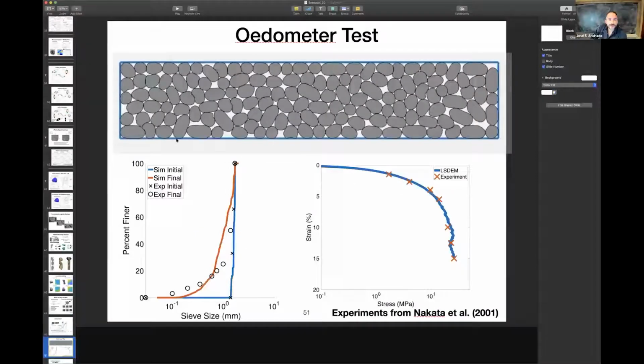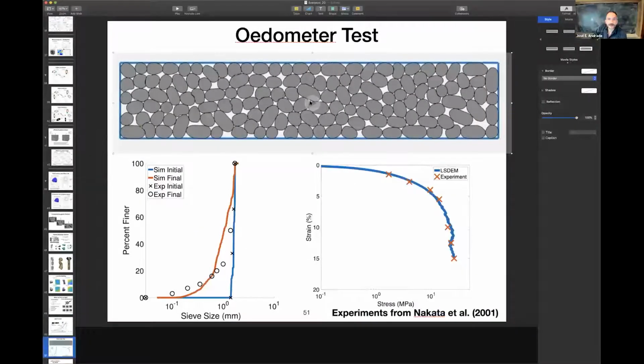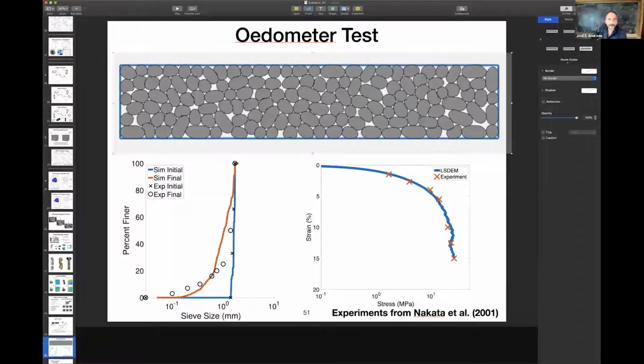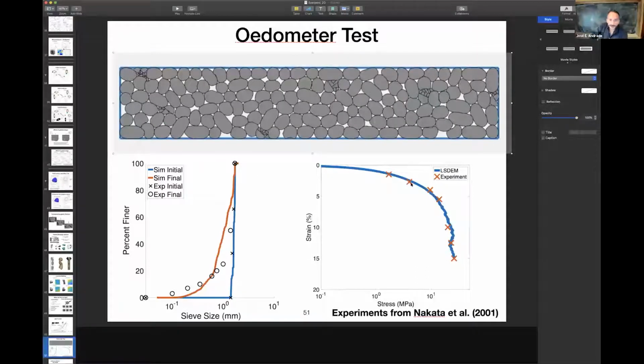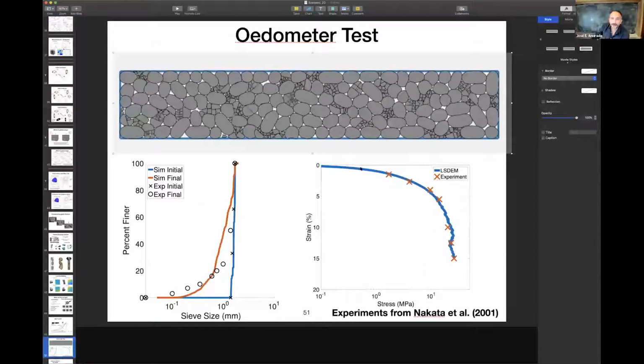model. You can do the same thing with the oedometer test. So this is the 2D version of that. People get things like stress-strain curves, like this one here on the lower right. Again, you see that the matching of the stress-strain curve is very good. Initial grain size distribution in blue, final grain size distribution in red. You can see that the model and the data agree really well.